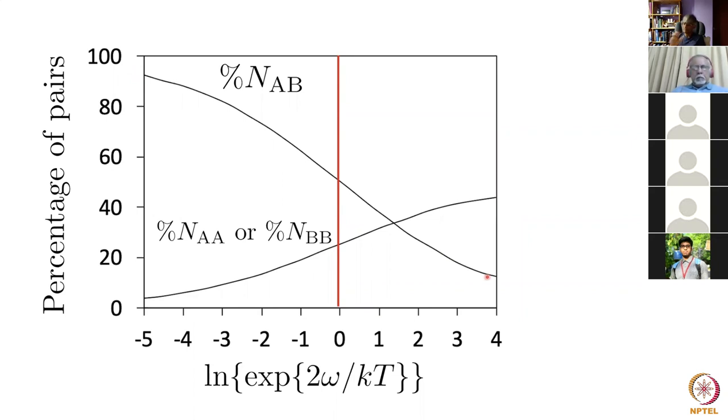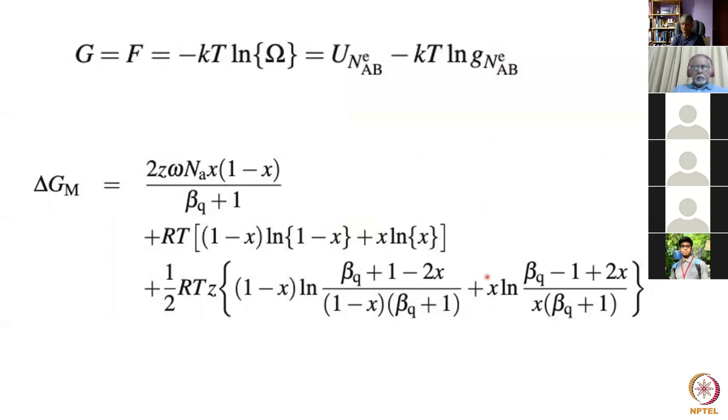So you can do a fairly rigorous calculation of the free energy using that partition function. This is the Helmholtz free energy, and if we are working at zero pressure, that's equal to the Gibbs free energy. We take the logarithm of the partition function. This term we've already determined from the omega and the equilibrium number of bonds. When we expand this, we have three terms here. This is our normal enthalpy of mixing if you ignore the denominator here, okay?